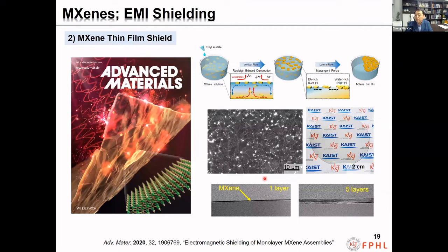In previous papers, the micrometer thick MXene films revealed very good EMI shielding performance. Nonetheless, the shielding mechanism was still not fully understood, mainly due to the challenge in preparing monolayer thick MXene films. Recently, we fabricated a large area, monolayer thick MXene film with uniform thickness by using interfacial self-assembly method. I will not explain the fabrication method in detail, but briefly, the exfoliated MXene flakes float and assemble each other on the water surface to form large area assembled monolayer film due to Rayleigh-Benard convection and Marangoni effect.